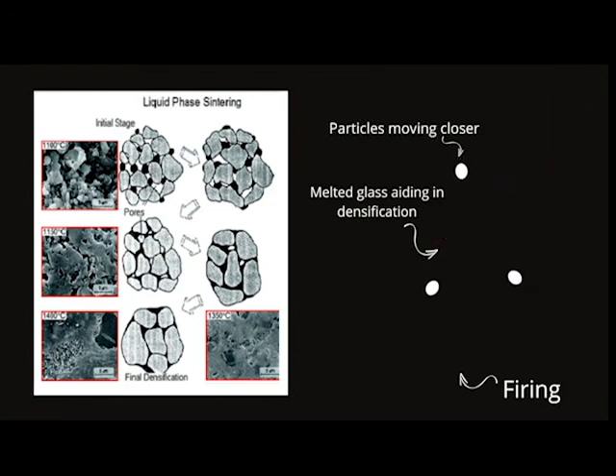To improve the properties of a material, it is often necessary to increase its densification through phase stabilization, active sintering, reactive sintering, and through liquid phase sintering. Phase stabilization is the use of another phase to prevent grain growth. Active sintering is the use of an additive to increase bulk transport, and reactive sintering is the use of additives to prevent loss of stoichiometry.